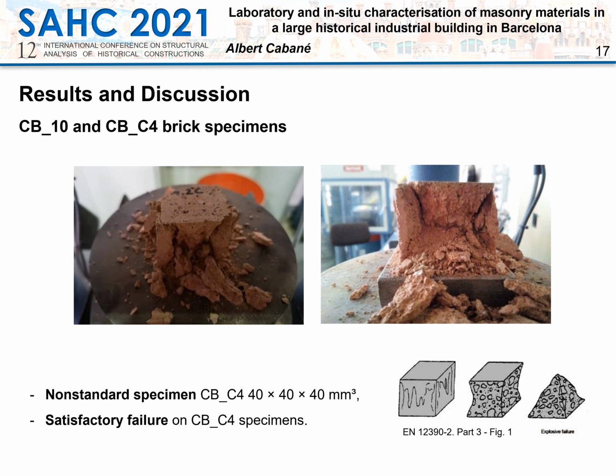Another stage of the experimental campaign considered compression tests on non-standard cube specimens. During the testing phases in the laboratory, the failure modes shown by the non-standard specimens were observed. The failure modes showed equal cracks on the four exposed faces and didn't show any tensile crack. These failures were compared with the indication in the European standard for satisfactory failures of concrete cube specimens.